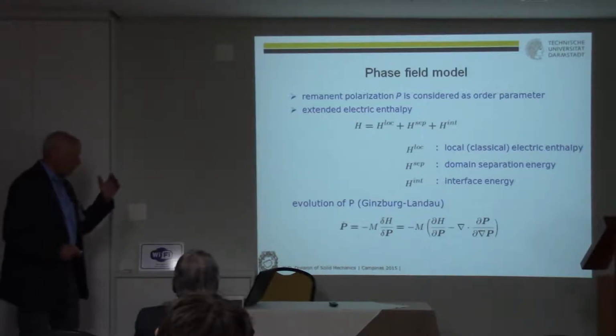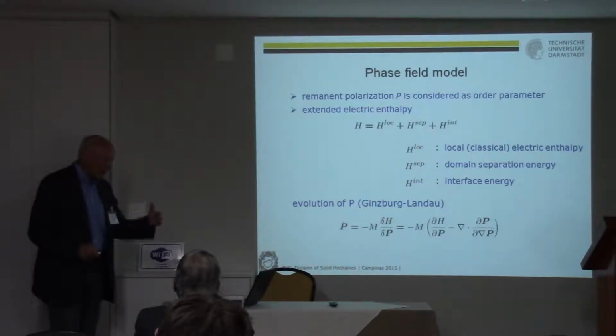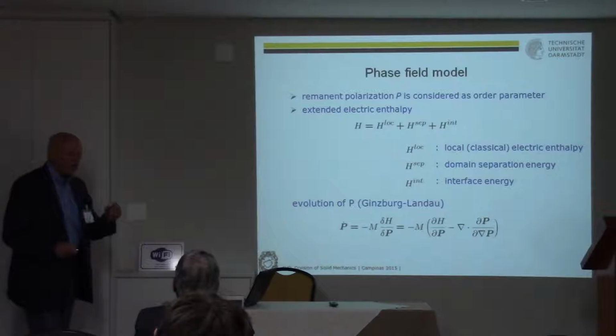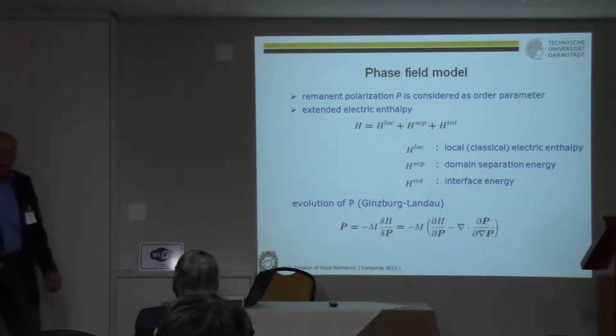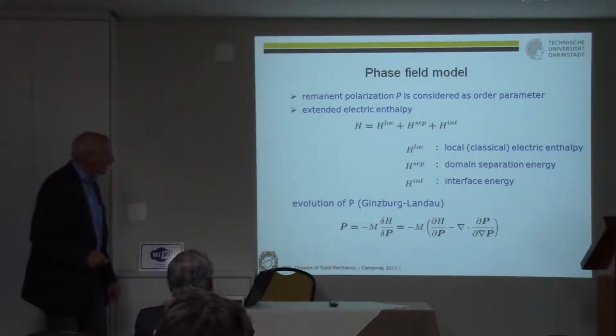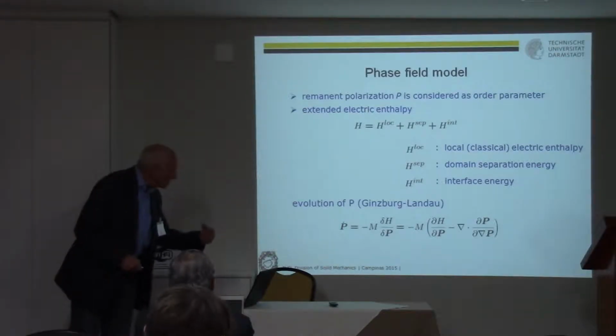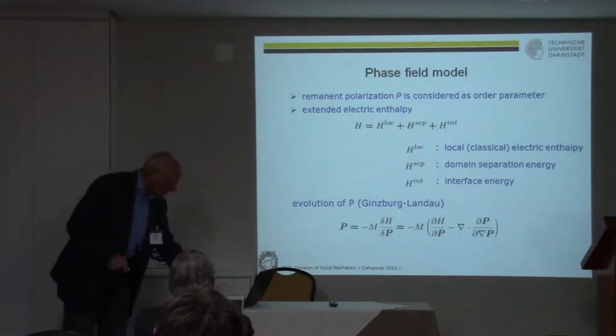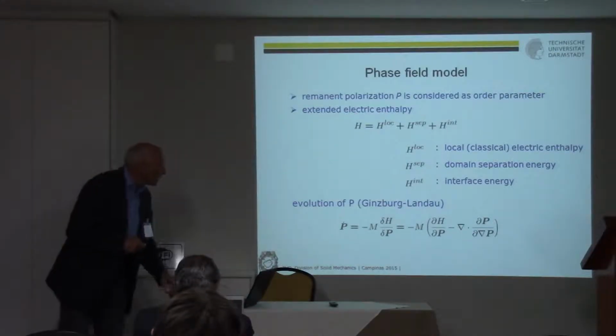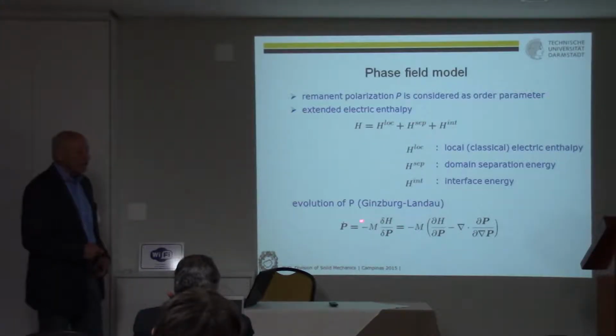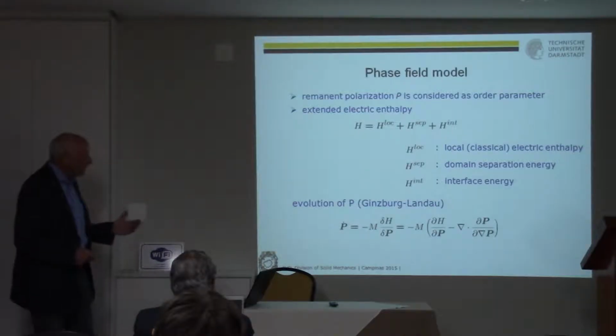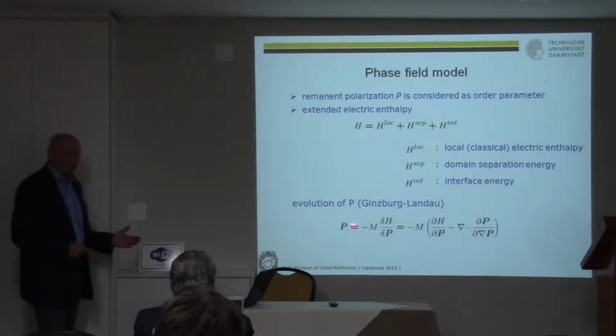Yeah. So you have to take into account that, say, a domain wall carries some energy, yeah, and so for separation and for taking into account the domain wall, you need energy terms, yeah, and P here is the polarization. This equation, yeah, is an evolution equation for the polarization, yeah.